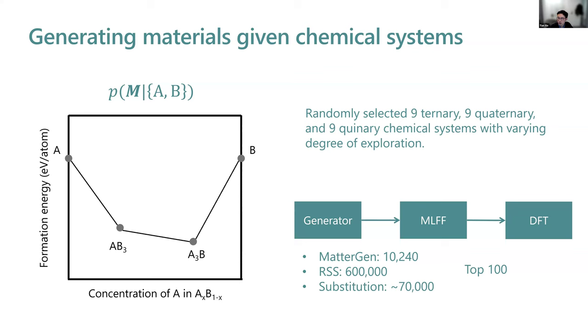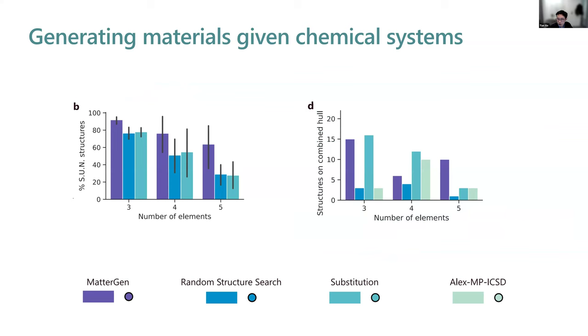To evaluate the performance of the model, we randomly selected 9 ternary, 9 quaternary, and 9 quinary chemical systems with varying degrees of exploration, varying numbers of existing materials that you discover. Then we benchmark our model, MatterGen, against two very popular ways of doing this type of material discovery. One is random structure search, and the second is substitution. We use all these three methods to generate different numbers of initial candidates, and then we apply a machine learning force field to relax them and filter them for the lowest energy structure. For the top 100 structures, we put them into DFT to see which ones are actually the most stable.